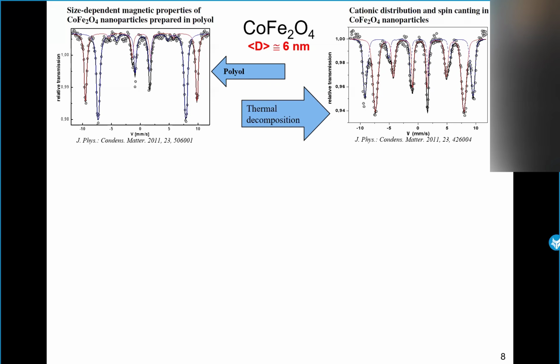But in the case of the magnetic nanoparticles prepared by thermal decomposition, we obtain a spectrum with more complex hyperfine structures. The spectrum here is characterized by broadened lines with some overlapping, but also with large intensity of the intermediate lines, order 5 and order 2. For this spectrum, we need to find the appropriate correlation between the distribution of the effective field for each subspectrum and the distribution of the spin canting, in order to have the information about the hyperfine field.